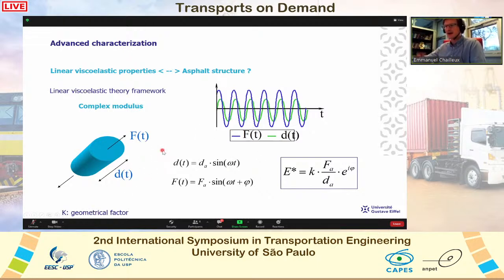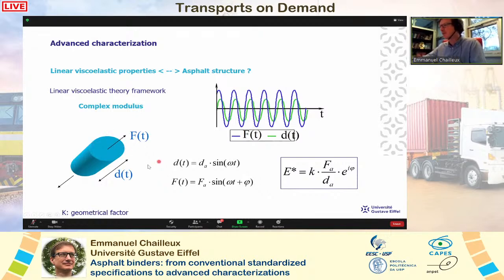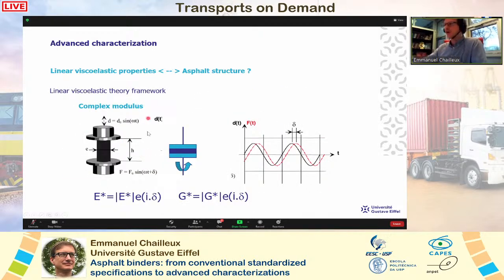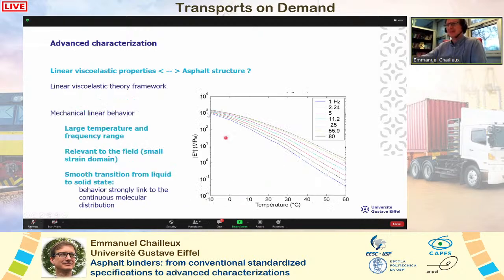Of course, here I have presented a tension compression loading mode, but you can use different modes of loading. You can also use shear loading, and it is commonly used for binder using what we call a dynamic shear rheometer. In this case, we measure the complex shear modulus using exactly the same system with sinusoidal force and sinusoidal response. These linear viscoelastic properties are very useful because they describe the mechanical linear behavior of a material, which can be measured over a large temperature and frequency range.